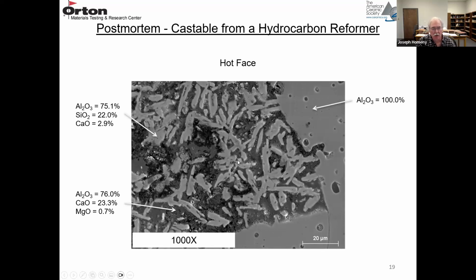And there's two phases in the matrix. The lighter needle-shaped crystals are mullite. So that's about 75% alumina and 22% silica. And then the darker gray region is where the calcium aluminate cement is. So you see alumina about 76% and calcium about 23%. So this is a high alumina aggregate with a matrix designed to form mullite and the residual cement.